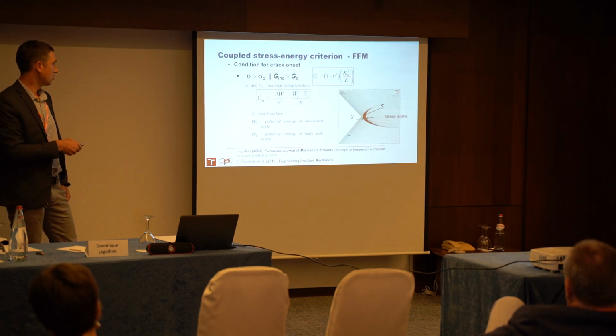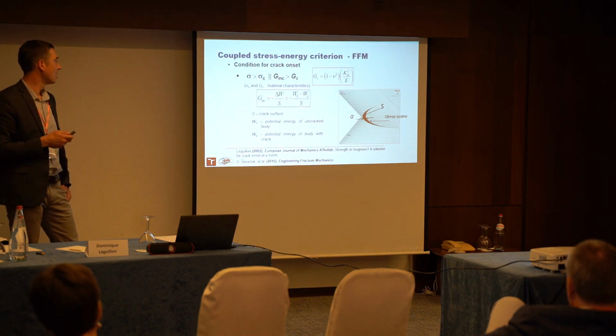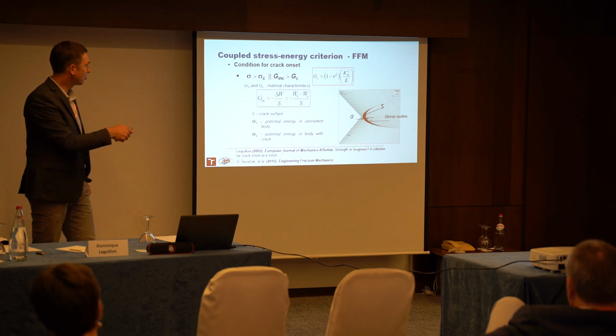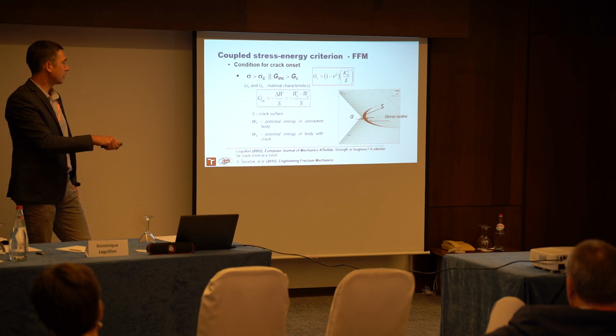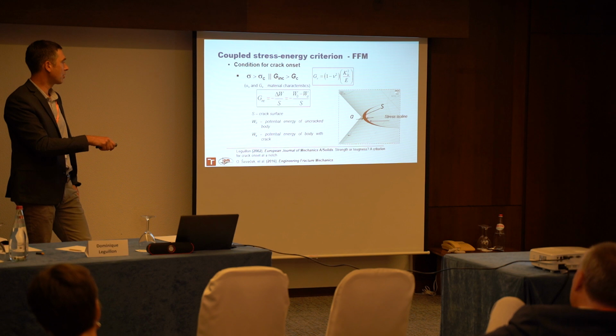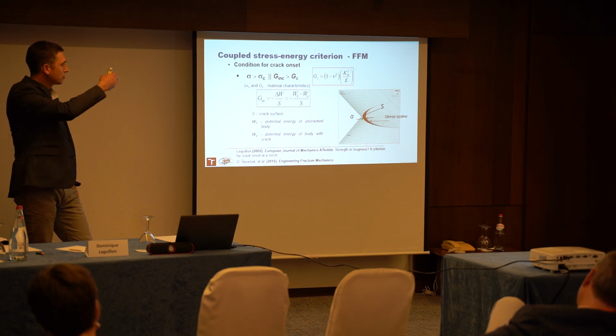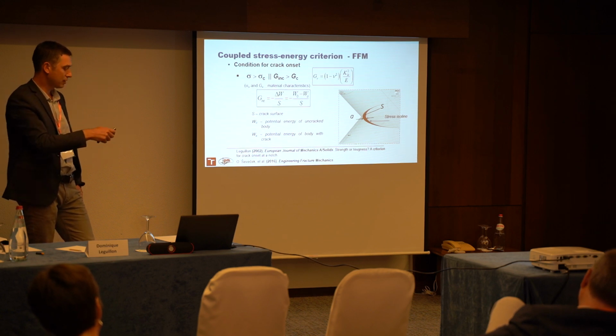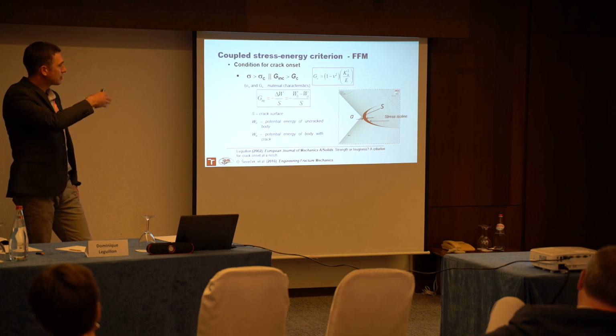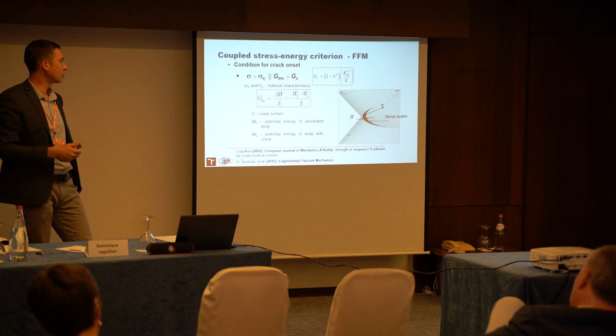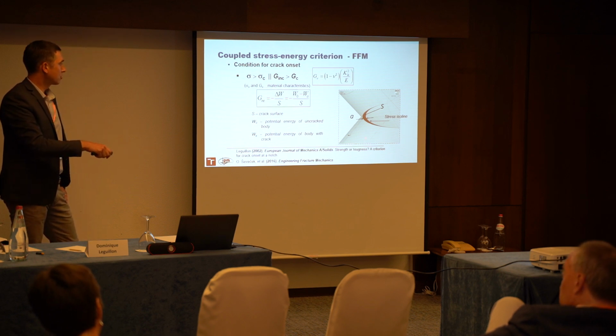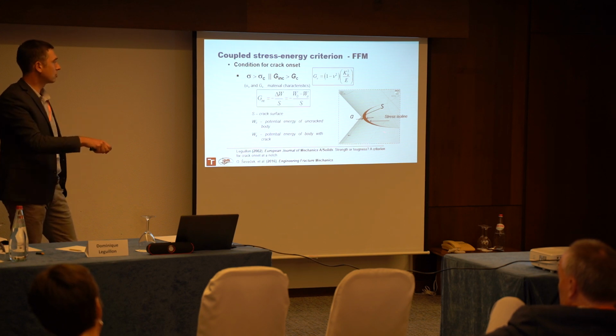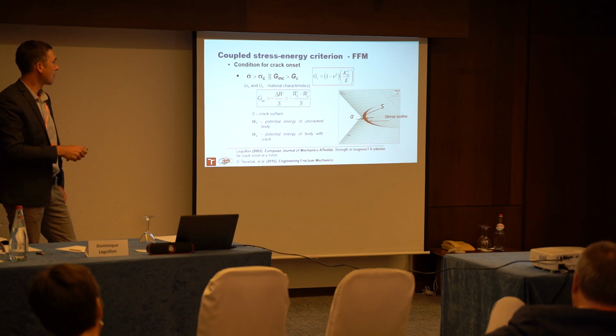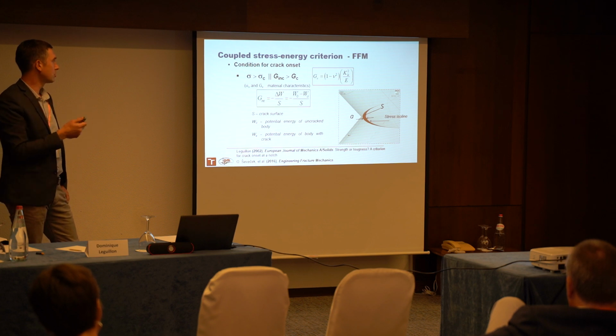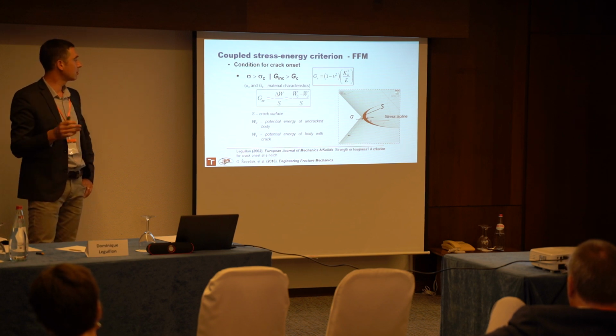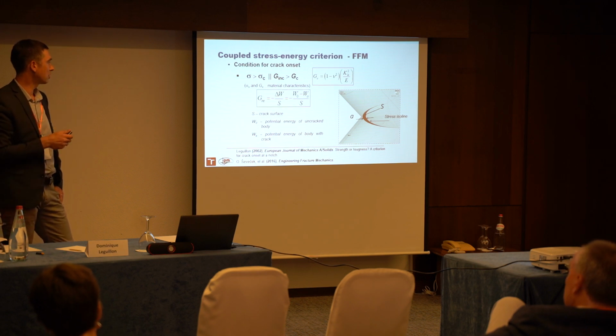So we took, here is the application of the coupled criterion, how it looks like. So this is the connection of the two struts, and we will now consider that the crack will have such a shape. This shape comes from the equality of stresses along the potential crack faces. So in fact, this crack face is a stress isoline, which comes from the mechanical loading of the deformed structure. We have some fracture surface, or we can relate this fracture surface to a crack depth in this corner, or in this location. And we have to fulfill the stress and energy criterion, as has been said today several times, so I will not go into more details. So both energy and stress condition must be fulfilled.